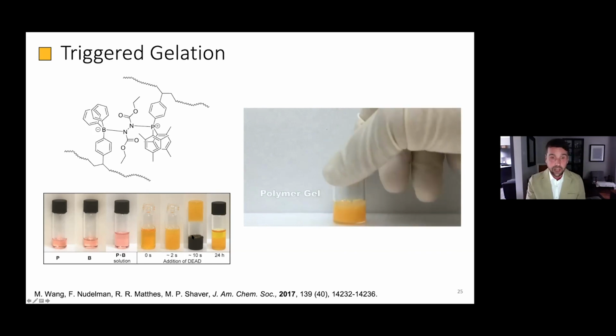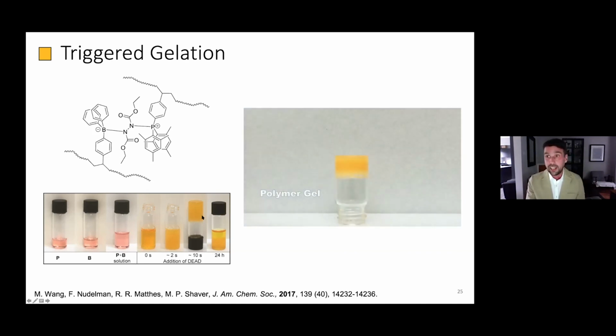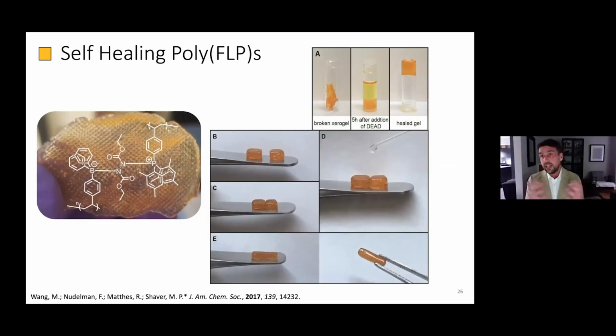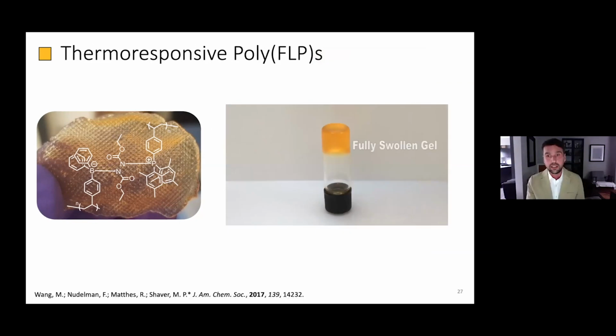You can see from the figure on the left that this changes over time. So I start with a kinetically trapped gel, and I get a rearrangement here that then pushes out some of the liquid and gives me a thermodynamically set gel that's much tighter and holds less liquid in it. So what this means is that this is dynamic, it's changing over time, and it does mean that these are self-healing materials. If I have a very dried down system, the chains don't have a lot of mobility, and so I have to add solvent and take a while to be able to rectify this. But if I have a wet system, one that's retained a bit of solvent in there, I can either squeeze it together or put pressure on it from a rheometer plate, or indeed add a little bit of solvent to get that interface functioning well, and within seconds have a fully healed system. So dramatically fast self-healing that's allowed to take place.